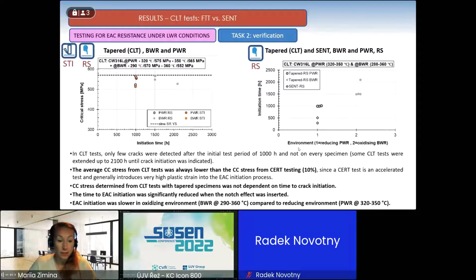And critical stress determined from constant load tests with tapered specimen was not dependent on time to crack initiation. The time to the initiation was significantly reduced when the notch effect was inserted, which is quite an interesting finding. And EAC initiation was slower in oxidizing environment in BWR compared to the reducing environment.